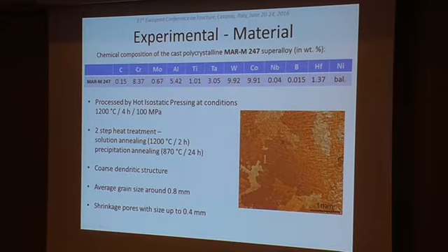Our alloy was MAR-M247 superalloy, which is a cast polycrystalline one with this chemical composition. The material was at first processed by hot isostatic pressing at these conditions, and after that followed a 2-step heat treatment consisting of solution annealing and precipitation annealing. And we obtained a coarse dendritic structure with average grain size around 0.8 millimeters, and also in the structure we found some shrinkage pores in size up to 0.4 millimeters.